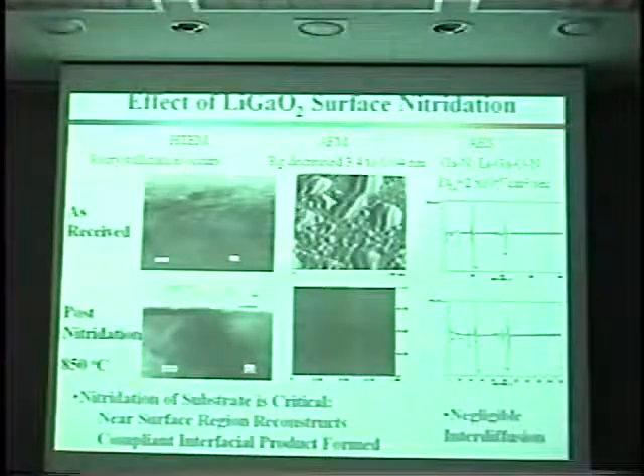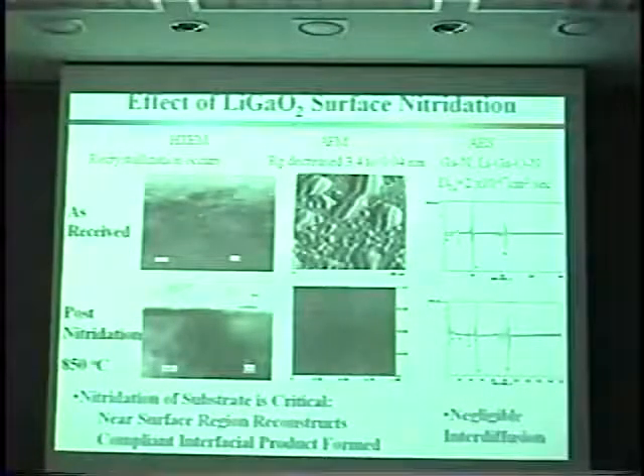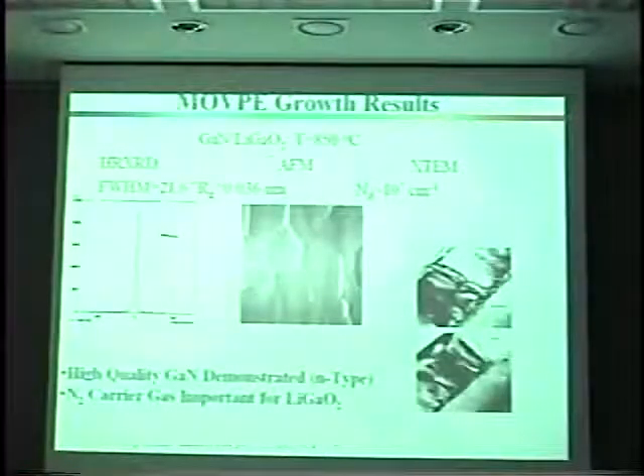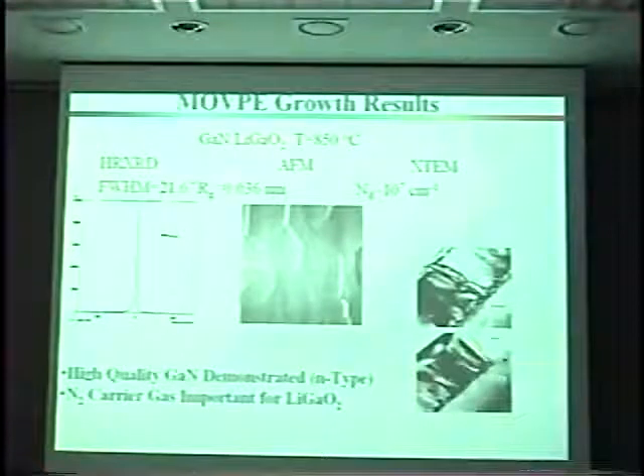Once you get that interface properly designed, you then can go and use traditional techniques for growth. Here's some MOVPE gallium nitride micron film that we grew on top of it. This is the lowest full width half max we've ever recorded for gallium nitride, about 21 arc seconds. That's approaching the quality of gallium arsenide.